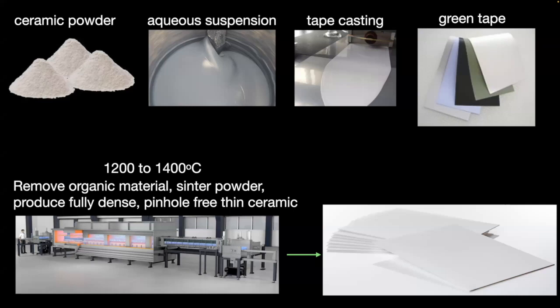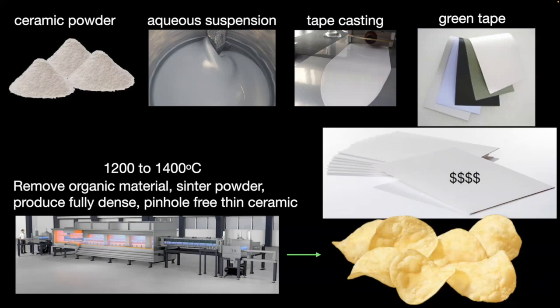That's quite difficult. And anybody who's done this kind of processing knows that quite often you get things that look like potato chips because you get differential densification when you're sintering because those powders are not mono-sized. And you may have variations in furnace temperature, which will also give rise to warpage and deformation. So to get a thin flat membrane is non-trivial and typically quite expensive.